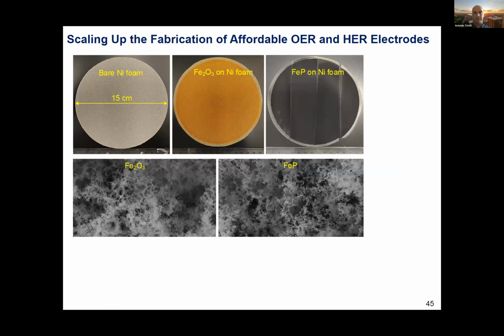That's a very good point, and that's a bit what happened here. So thank you so much, Drew, for the very good comments. So here we start with the fractal structure of iron oxide, and you can see it here in this example. And then we post-process it by placing it in a furnace with a nitrogen carrier flow and a phosphor source, and we convert it in a fractal structure of iron phosphide.